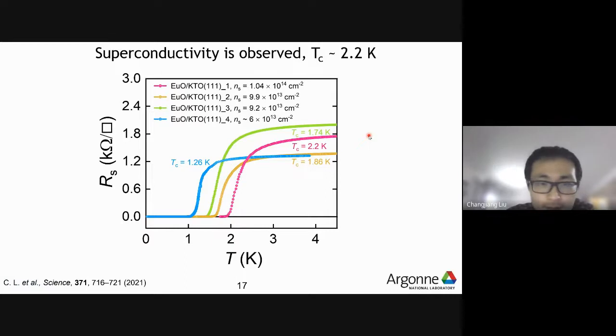So now this is the measurement I just showed you earlier on the EuO KTO, performed at a lower temperature. You see that there are 4 different samples. All of them are grown on a KTO 111 surface, which has the honeycomb-shaped crystal lattice. In all of these samples, the sheet resistance goes to 0 as you lower the temperature further, and the transition temperature can be as high as 2.2 Kelvin for the sample with a doping level of around 1 × 10¹⁴ per centimeter squared. So this interface is now showing a superconducting behavior.